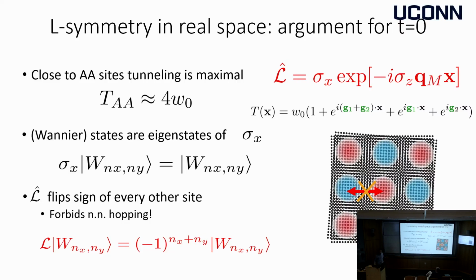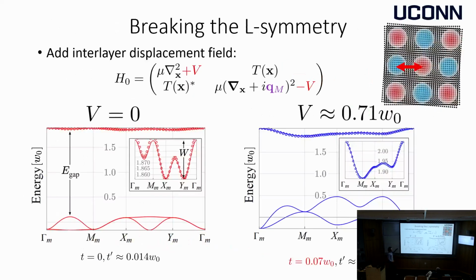And once we understood this, we realized you can break it by hand. Specifically, you can apply a displacement field and make the chemical potentials of the layers different. What we see is that we can induce a nearest neighbor hopping on this lattice that becomes sizable. In this case, it's 5 times larger than the next nearest neighbor ones.